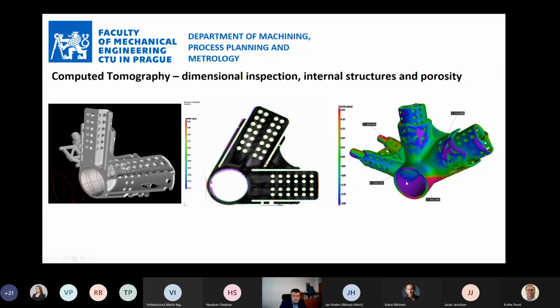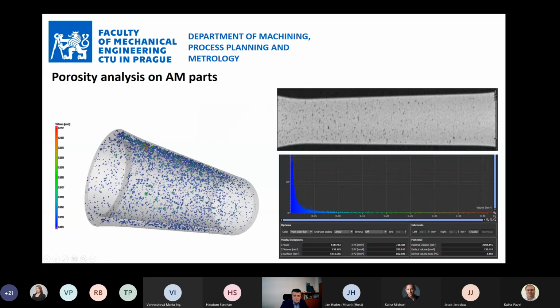So this is a very quick analysis on such a part, which is a bicycle part, the midsection of the bicycle printed from aluminum alloy. Scanning in this case is something like 40 minutes, maybe 50 minutes. And this kind of analysis is another 5 minutes. So this is a very quick analysis to get, and you have complete information of the outer shape and also of the internal cavities. Then, of course, using computer tomography, you can also see inside the part. So here you can see some cross section of the part, which actually in the software is live. You can go through the data with some viewer software that is freely available. So once you have the scanning data, you can work with them independently, basically, of us.